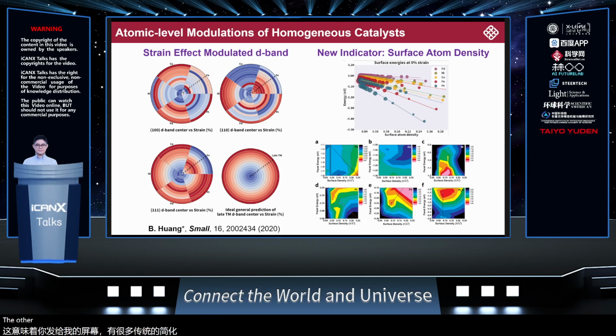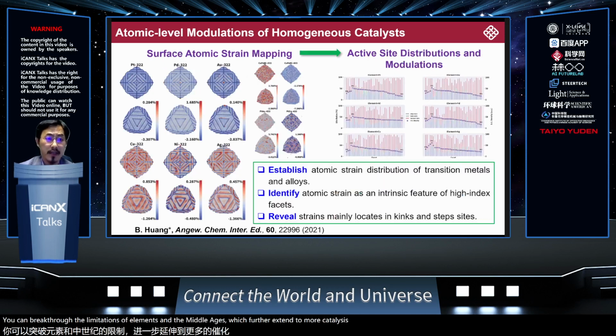To overcome this challenge, we propose a new parameter, surface atom density. And this parameter linearly correlates the different high index facets with the surface energies and electroactivities. It can break through the limitations of elements and the morphologies, which further extends to more catalysis processes and systems.